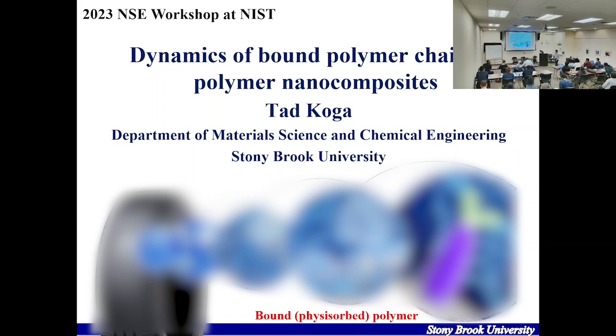Today, I want to talk about our ongoing research, especially using neutron scattering, neutron spin spectroscopy. Our target is the automobile tire. Our focus is here. This is the polymer chain at the filler surface. We want to see what's going on at this interface, the polymer and filler interface. Our target is what's called the bound polymer. Some polymer physisorbs onto the filler surface, and this plays a crucial role in the mechanical property. Even though the thickness is only a few nanometers, this is the key for the automobile tire, especially its mechanical properties.